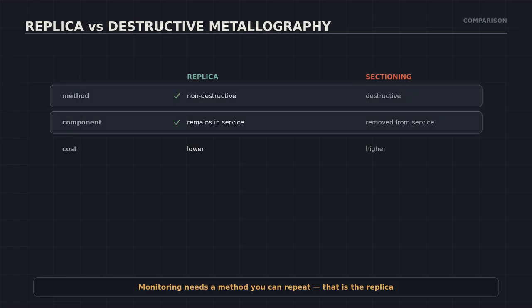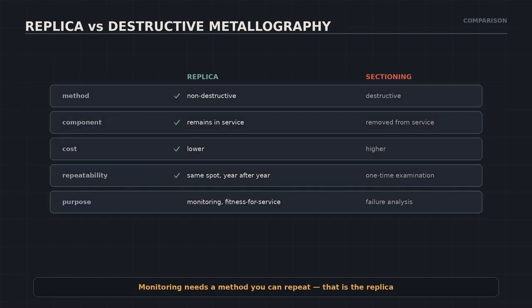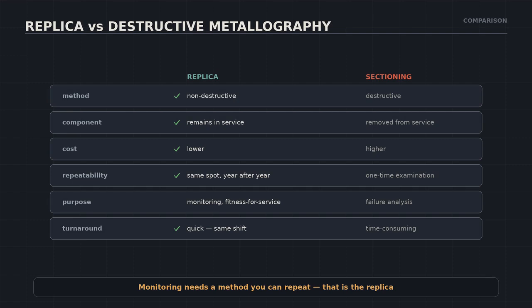Why replicas instead of cutting samples? Sectioning metallography is destructive, the component comes out of service, costs more, and gives you one examination, one time. Replica metallography leaves the component in service, costs less, and, most importantly, is repeatable. You can examine the same spot, year after year, and watch trends. Sectioning is for failure analysis after the fact. Replicas are for monitoring, before the fact.